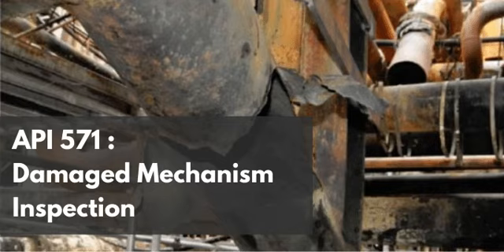So what's the fix? To mitigate the weld vulnerability, engineers must carefully and ruthlessly regulate the 300 series weld procedures. It is a delicate, uncompromising balancing act during fabrication. Because you need some ferrite to prevent the hot cracking during the initial construction, right? You do. But the absolute necessity for long-term integrity is keeping that ferrite phase strictly capped.